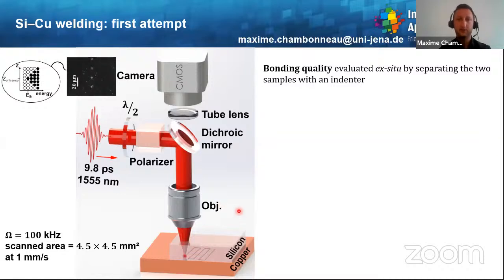And this objective lens is also used for a similar microscope shown here, which works in dark field, and we can basically acquire some dark field images, as you can see here, and position the hypothetical focus with respect to the surface. Then we evaluate the bonding quality ex situ by separating the two samples with an indenter. So let us have a try.